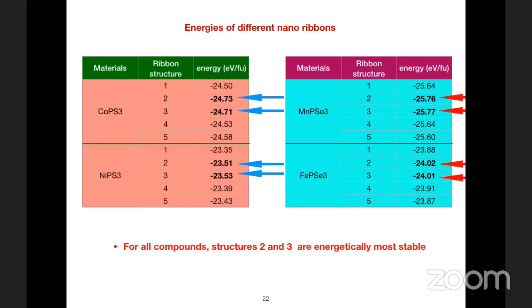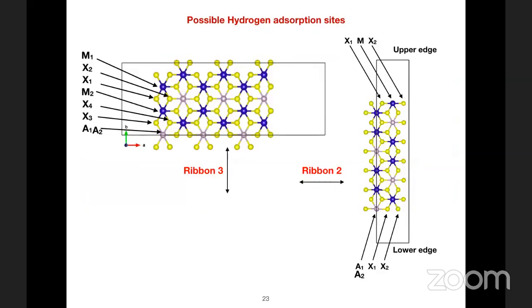So what we do is, first, of course, we calculate the energies of these 5 structures. In every case, it turns out that structures 2 and 3 have the lowest energy. They are close to each other, whereas the other structures have higher energy. So subsequently, we focus only on these 2 structures, structures 2 and 3. We identify possible sites at the edges where hydrogen could be adsorbed, then adsorb hydrogen and calculate the delta GH for the sites.